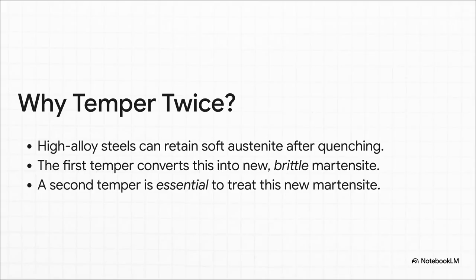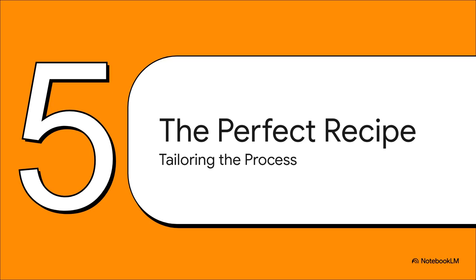But why temper twice? You might hear about that sometimes. Well, with some high alloy steels, the quench doesn't convert everything. You're left with these little pockets of soft, unstable austenite. Here's the crazy part. The first temper actually transforms that leftover stuff into new, brittle martensite. So you have to do a second temper to take care of that new, brittle stuff. It's absolutely essential to make sure the tool is uniformly tough all the way through. So as you can see, this isn't just one single process. We're really choosing the perfect recipe, tailoring the entire transformation to the specific job the tool has to do.